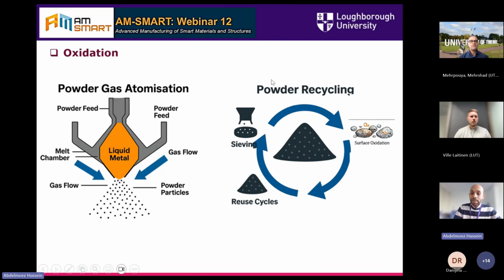The second thing that I have found is how many times you are going to use your material. If you use your material for the first time, probably you can get good magnetic properties from the resultant additive manufactured part. However, I was very keen on every build to get the material isolated from the atmosphere and powder storage, and to keep it away from oxides. Yet, what I find is that every time I start with the second build, third build, fourth build, the material properties start to be different, even slightly, which leads to poor magnetic properties with recycling. So powder recyclability is another issue that we can find.